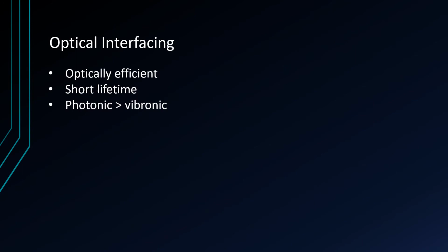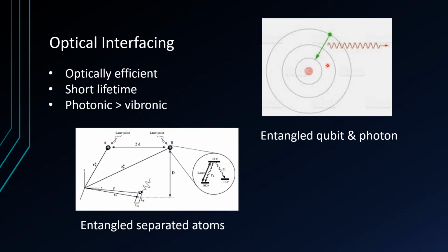What makes zinc oxide donor qubits special? One thing that makes them particularly nice for computation is their optical properties. They have very high optical efficiency, a radiative lifetime of only about a nanosecond, and a low Huang-Rhys factor, which measures the extent to which electronic transitions generate phonons. This means that the donor-photon interactions are predictable and reliable. Zinc oxide donors can be entangled with photons that they emit. If excited to an exciton state and allowed to radiatively relax without measurement of the emitted wavelength, the qubit state and photon color are now perfectly correlated.